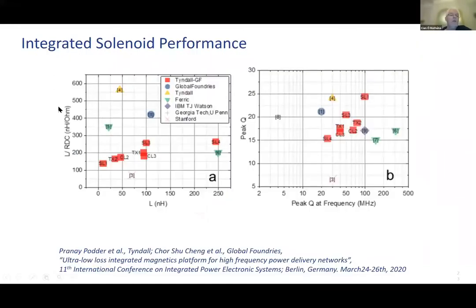And if you look here, we're showing two plots that are comparing different inductor technologies from different groups around the world. So we're plotting the inductance here against what we would call the inductance per DC resistance. And you can see here that the Tyndall device has low inductance, which means it can operate at very high frequencies, and it has the best inductance per DC resistance of the different ones that we looked at. And if you look at it from a Q point of view, again, the peak Q, we had one of the highest Q factors, and this compared with a device that we built for one of our customers. So we were able to get, in two instances, the highest Q that had been reported at that time.